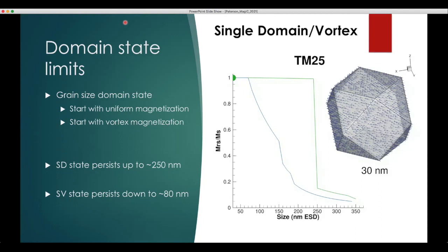And so that might actually suggest that switching between either thermal and AF demagnetization might allow us to do some preferential cleaning. But it's not going to be quite that simple. And I think this is something that needs to be delved into in more detail. And if the drop in the coercivities for the sort of unstable zone is consistent, this kind of AF cleaning might work. I'm not sure if the drop is going to be large enough that it will be practical.